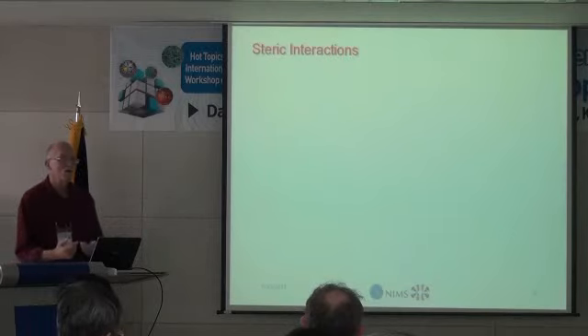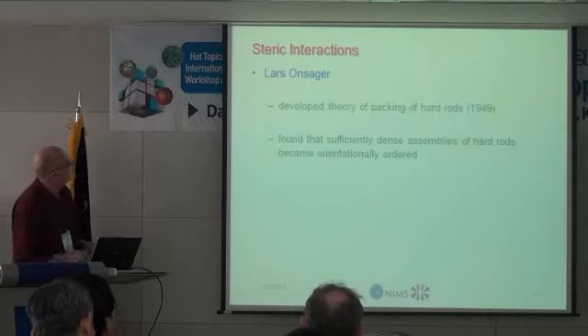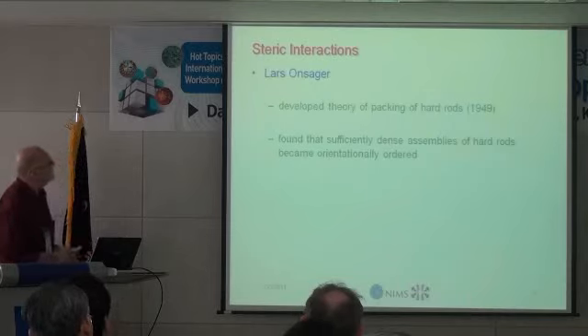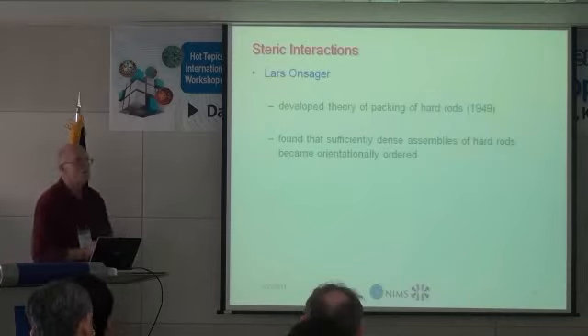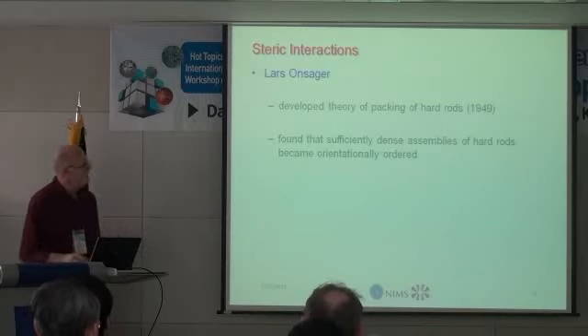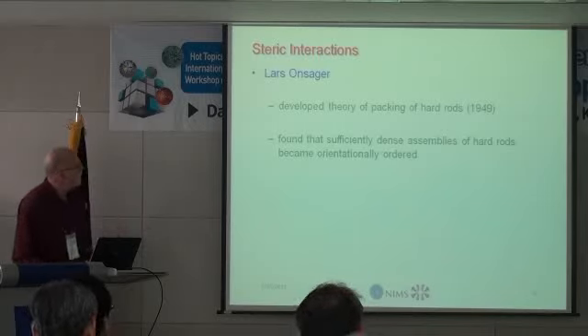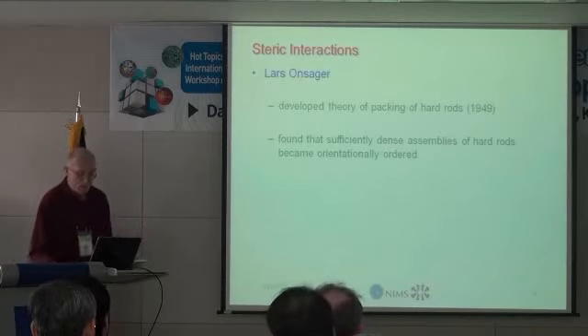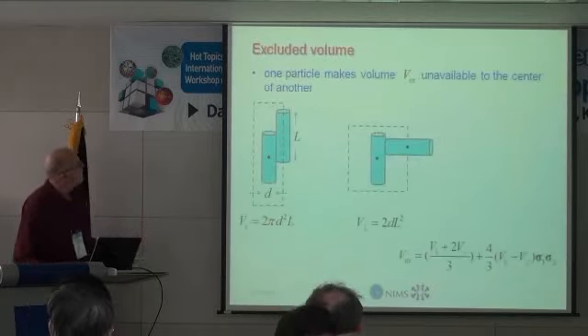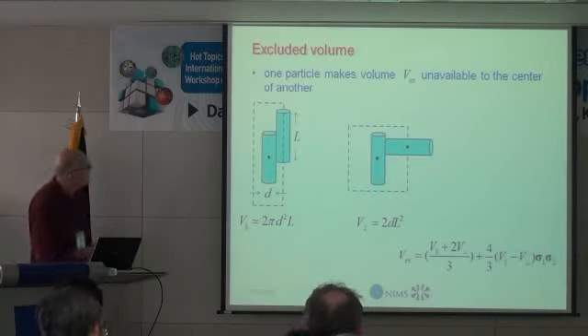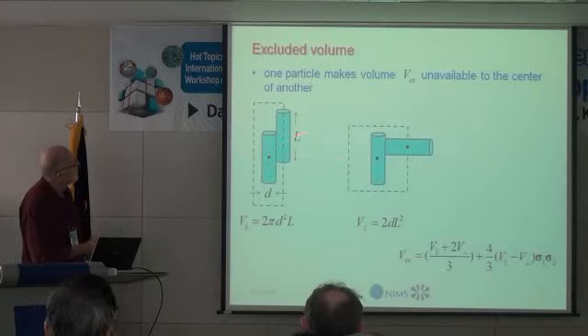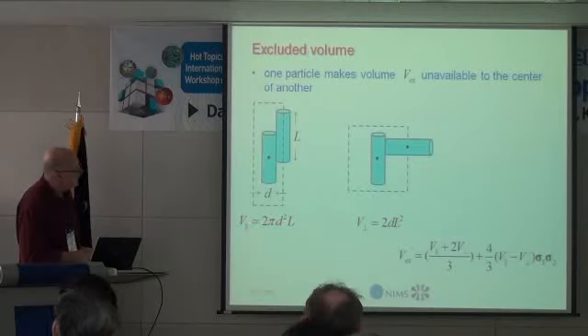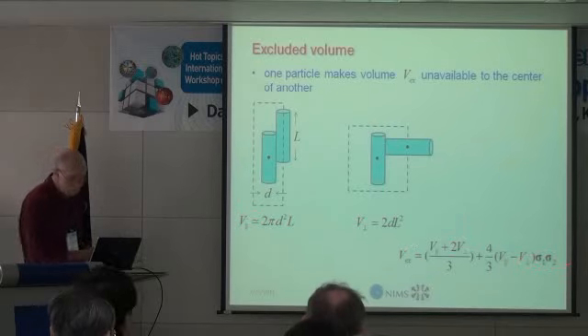Now, in addition to attractive interactions, there's also hard particle interaction. And Onsager developed the theory of packing of hard rods back in '49. And he found that if you pack enough of these into a fixed volume, they will also order. And the basic idea is that if you have two rods, one of them will exclude a certain volume to the center of the other, and this excluded volume depends on orientation. To lowest order, one could write it in this form.